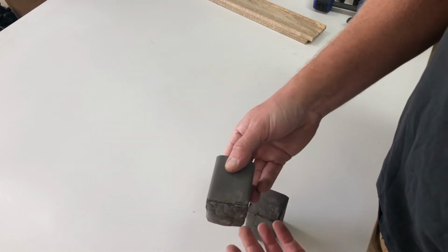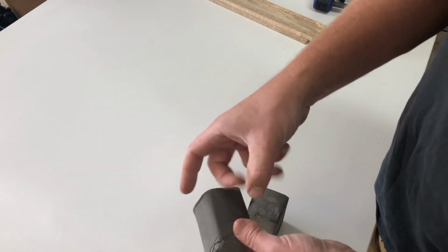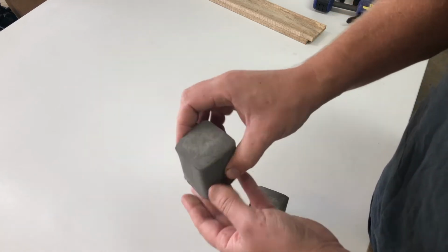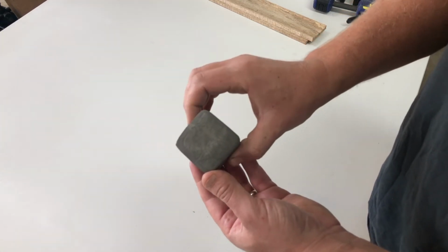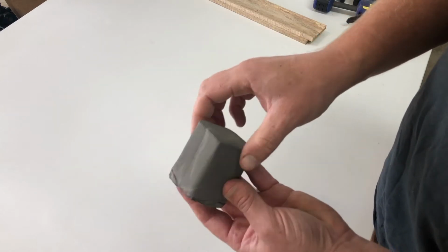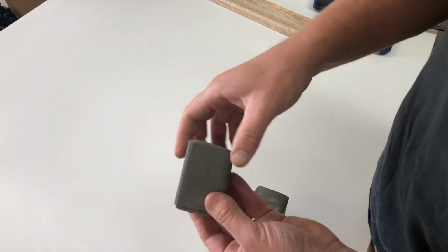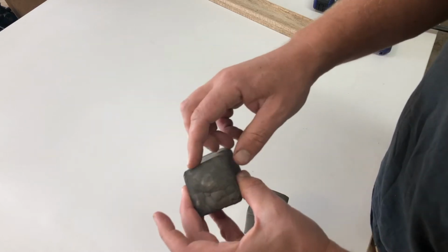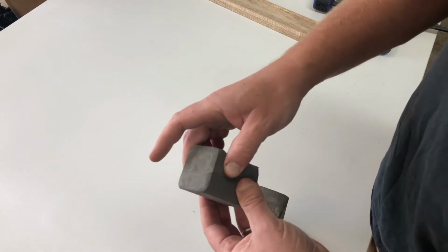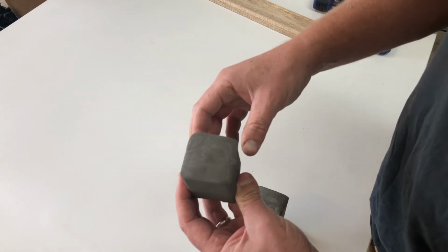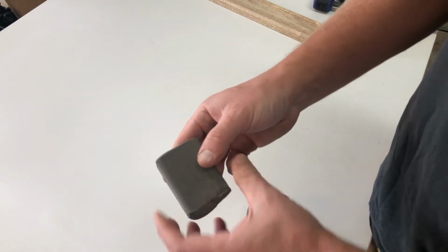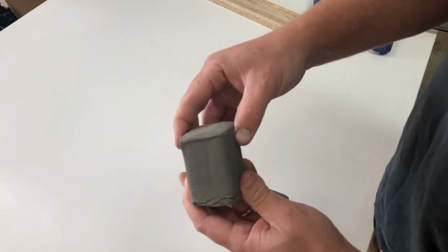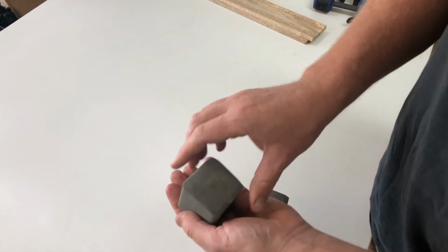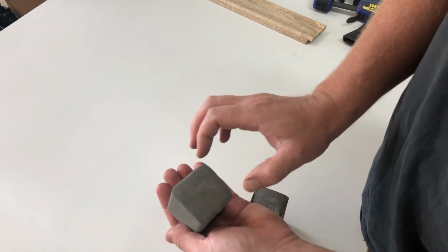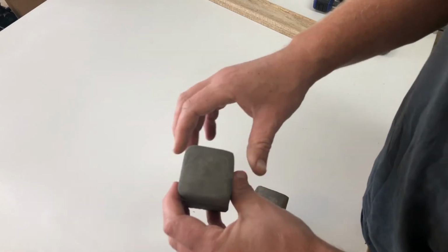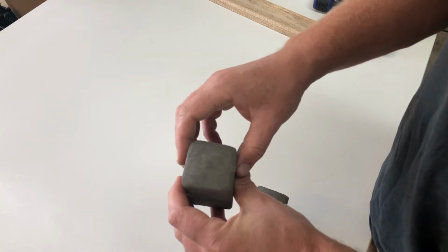So at this point, these are very solid, and they're rock hard essentially. And you can see there's been a little bit of distortion. This was the end that paper got a little wrinkled up. So a little bit of distortion in the drying process, but we don't have any cracking, no major warping here. And these are still just barely too large to fit in the 2-inch square tubing that I'm going to be using.